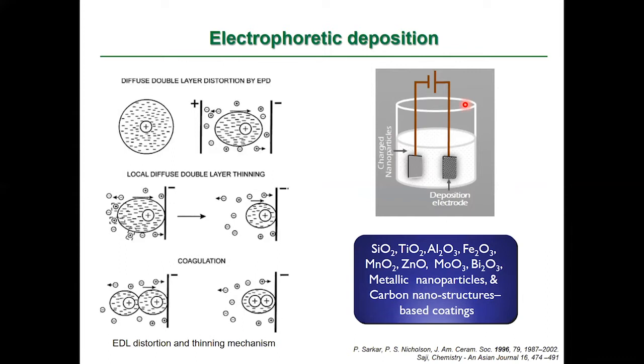So electrophoretic deposition is an excellent coating approach. It is actually a colloidal process where suspended and charged particles or molecules undergo electrophoresis and get deposited on the oppositely charged electrode. Electrodeposition or electroplating depends on the Faradaic process, that is, a deposition of ionic species, but here it is a deposition of charged particles. Similar to all the electrochemical methods, it also depends upon a 2 or 3 electrode electrochemical setup. Superhydrophobic coatings were fabricated using ceramic oxides, metallic nanoparticles, or carbon nanostructures-based coatings by EPD, electrophoretic deposition.